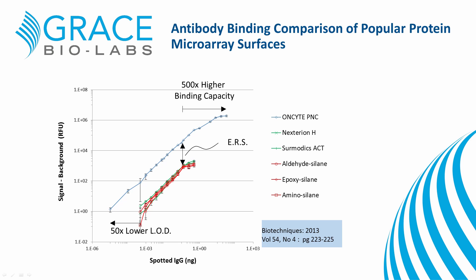Due to these various characteristics, ONCYTE PNC outperforms other commonly used protein array surfaces, including hydrogels and functionalized glass. ONCYTE PNC has 500 times the protein binding capacity of these other surfaces. This can extend the linear dynamic range of functional assays nearly 100-fold. Additionally, we observe much better sensitivity with ONCYTE PNC, with a 50-fold lower limit of detection. These gains in performance are primarily due to the high binding capacity of ONCYTE PNC and the retention of protein structure.